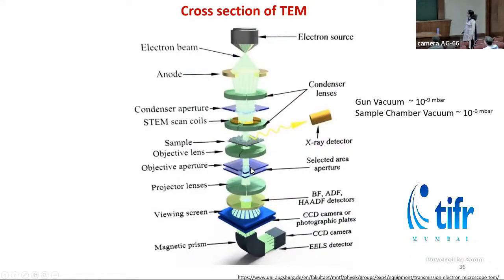magnify the image. There are different detectors like bright field, annular dark field, high angle annular dark field. So these are the Z contrast detectors in TEM. Here is the CCD camera, which is used for imaging, and the electron energy loss spectrometer sits here. This is the X-ray detector to detect the elements present in the sample. This whole assembly again sits in a high vacuum, where the gun is at 10 to the power minus 9 millibar vacuum level, and the sample is at 10 to the power minus 6 millibar vacuum level.